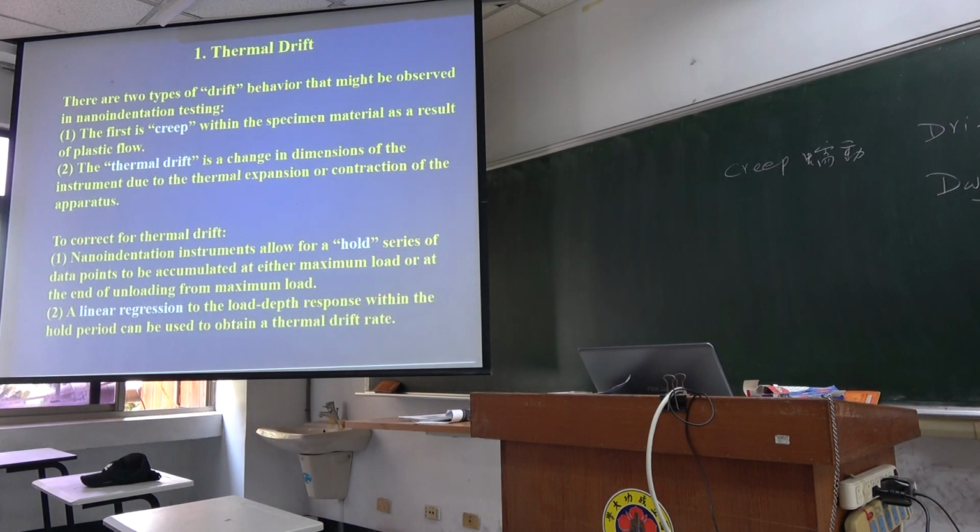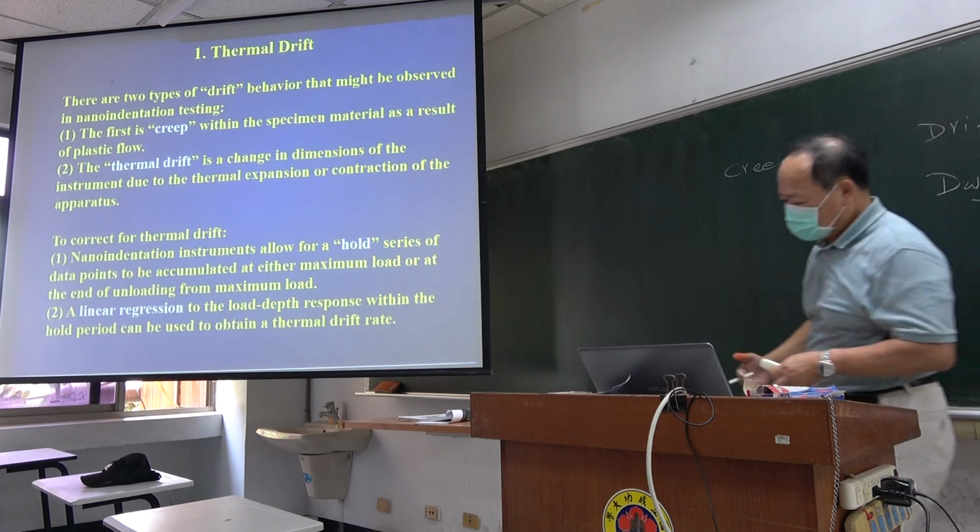So in the later section, the dwelling process means that when you have loaded up to the maximum load, we hold this maximum load constant for a period of time. This time may depend on your material. If your material is soft, you make the period of time long. If your material is brittle, in this case, you can shorten your dwelling process time. Okay.